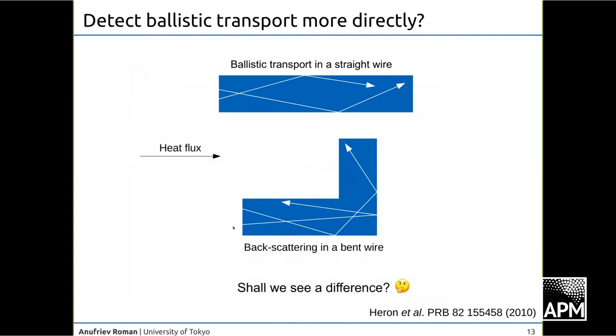What if we compare conduction in a straight wire with conduction in a wire with a turn? Of course, it's a super cartoonish picture, but just to give you the idea that in the straight nanowire, the phonons are expected to travel without obstacle, whereas in the bent wire, phonons are expected to be scattered backward. And that should be detectable in our experiment. We should see that this one is slower than this one. This was done first in 2010, but only at ultra low, sub-Kelvin temperatures. But we were curious, what if we do it at higher temperatures?